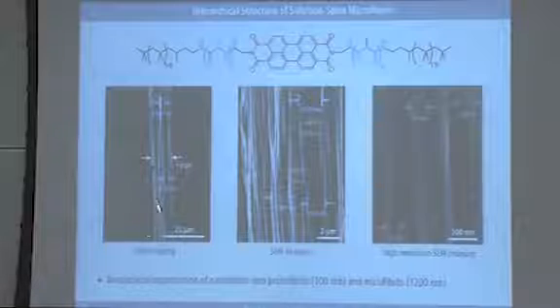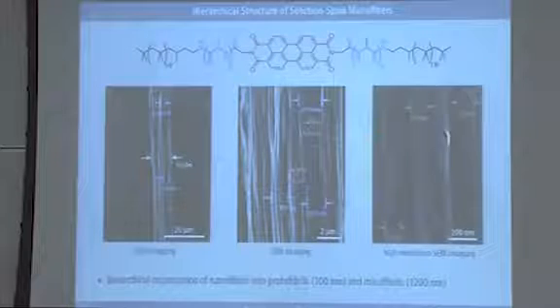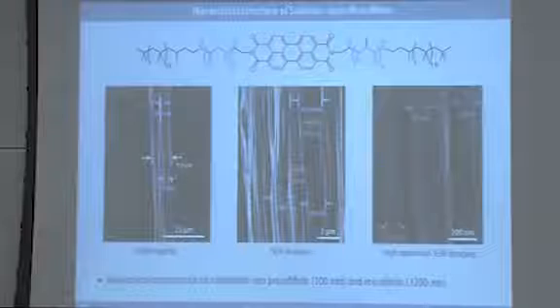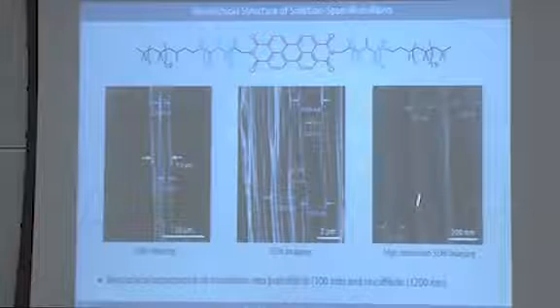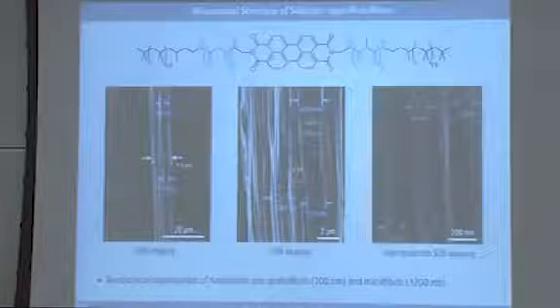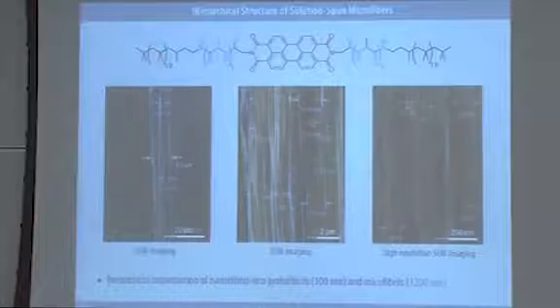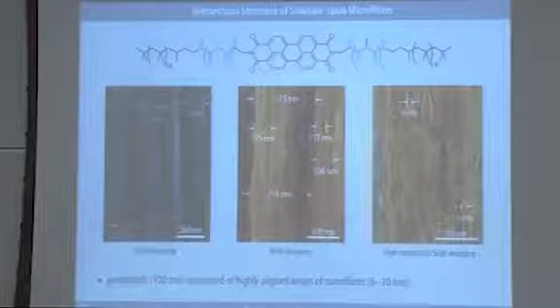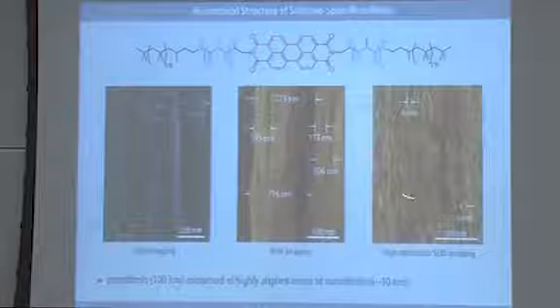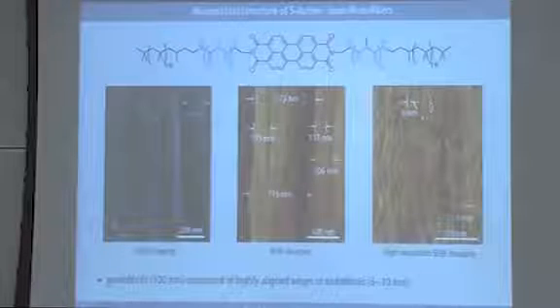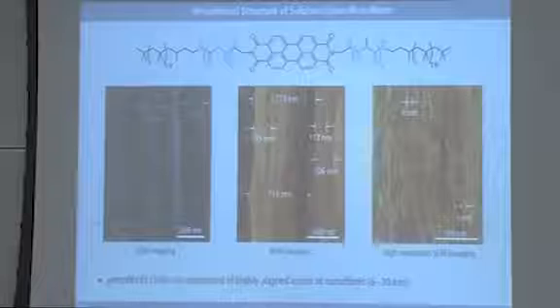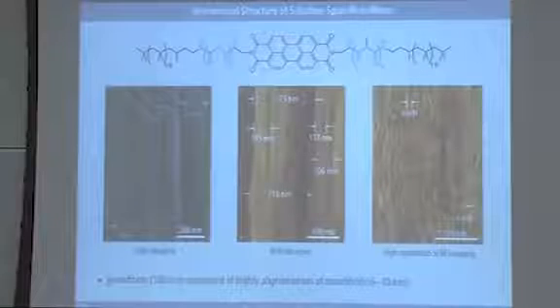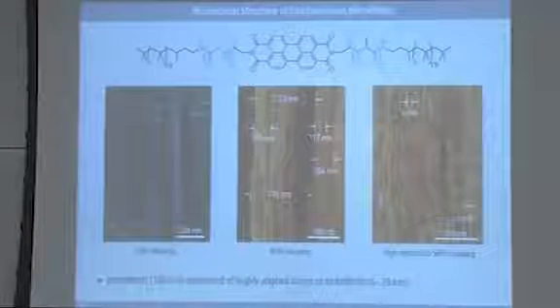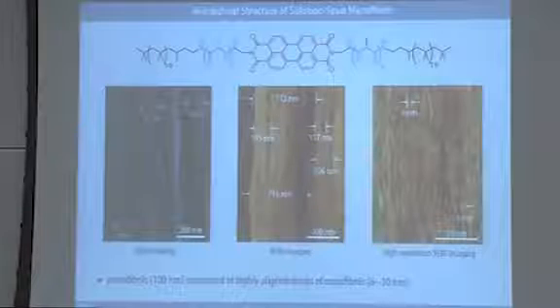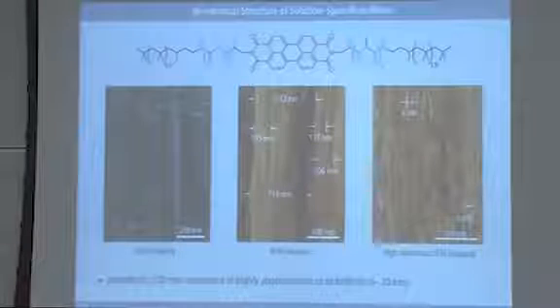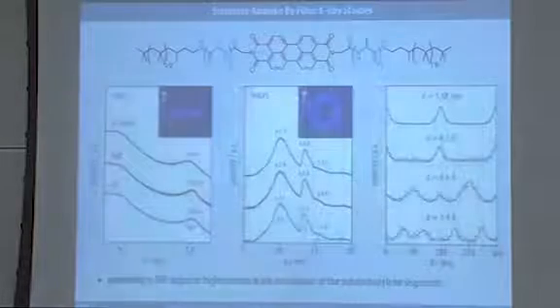SEM imaging of the microfibers shows that they have some sort of a hierarchical structure, with larger bundles that are composed of smaller bundles. And if you zoom into these smaller bundles, shown again here by AFM imaging, you can see that they consist of a highly aligned array of the nanofibrils that we had processed from solution. So it is not a surprise that we get nice data from polarized optical microscopy and IR microscopy.